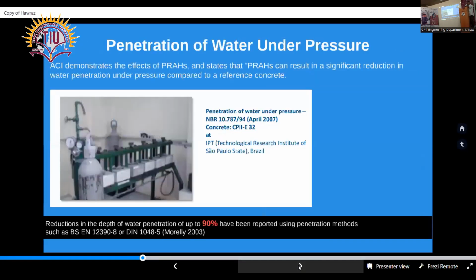To show the effect of crystalline, actually, we have a test which is called the DIN 1048-5, in which, as shown in the photo, cubes of concrete are exposed to water pressure, and it will usually stand up to 72 hours. After 72 hours, the cubes are broken in part, and the depths of water penetration are recorded. So according to ACI, reduction in penetration of water up to 90% has been recorded by modifying the property of concrete and making the concrete self-defending.